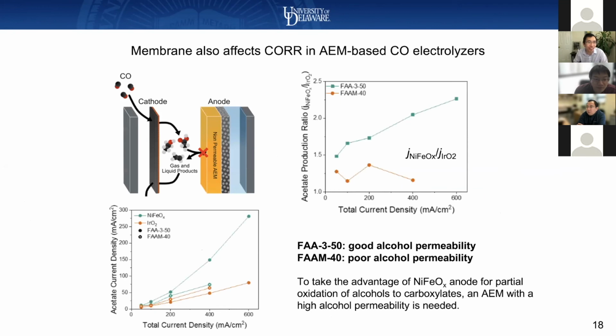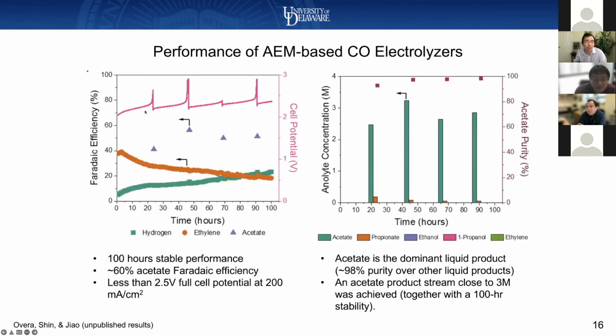So let me tell you the story here. Sorry, I didn't get a chance to get into it. When you see the spike at this point, because the pH is close to neutral, about 9 to 10, we actually lost most of the iron from this system. The catalyst we made starts with the nickel form, and we deposit the iron onto it, but at near neutral pH, most of the iron actually left the system. So to get a more flat performance, we limited the concentration of the acetate product stream not to 3 molar, but to 2.5 molar. So the pH does not drop that significantly, and we can maintain most of the iron on the catalyst.